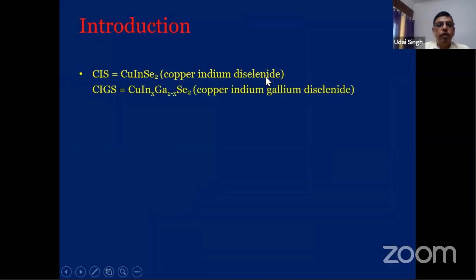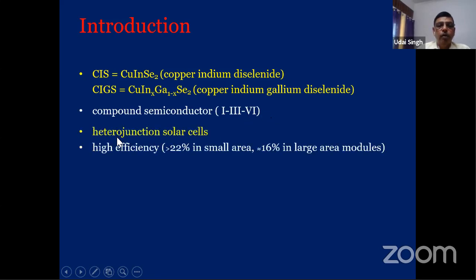If you see this material, it is basically copper indium diselenide. Now if you replace some of the indium by gallium, it becomes copper indium gallium selenide, so you can vary the band gap of the material. It's a compound semiconductor of the 1st, 3rd and 6th groups. It's basically a heterojunction. Silicon is a homojunction, because you take a p-type silicon wafer and then diffuse n-type. But here copper indium gallium selenide is a p-type material, then you have a different n-type material, so when you make a p-n junction, it's a heterojunction.